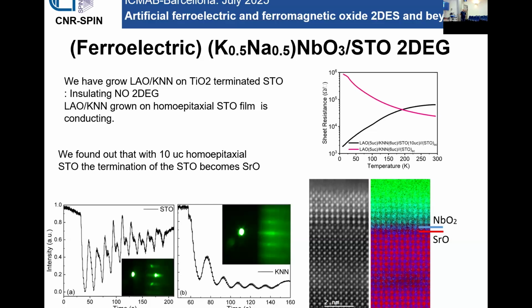And the reason why this happens is because essentially there's a switch of termination on the film. On the film, the termination changes from TiO2 to strontium oxide, and the termination is complete when essentially you have about 10 units of STO on top of your epitaxial STO. This depends also on the deposition conditions, but in our deposition conditions, which are high oxygen pressure and 750 degrees with pulsed laser deposition, you can also see this switching during the growth, because you see the RHEED oscillation, with the appearance of another periodicity, which is related to the other termination.